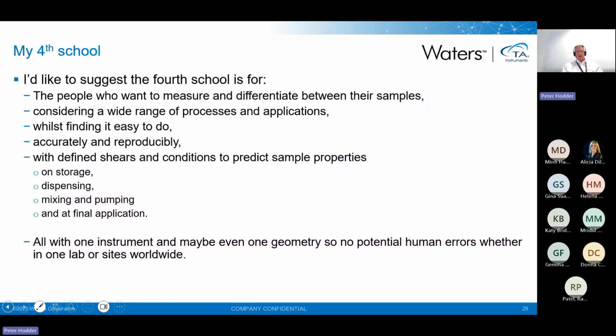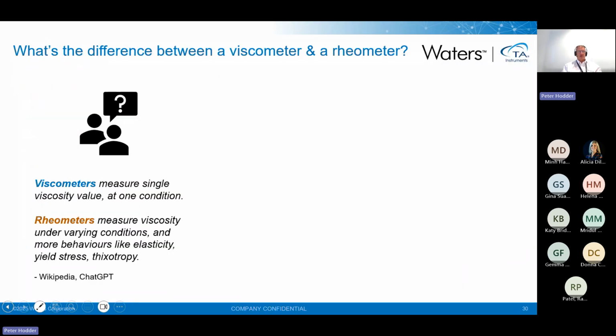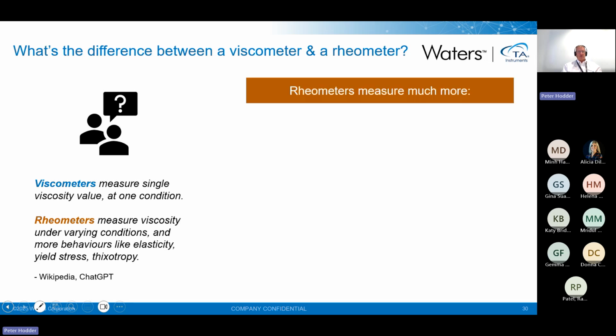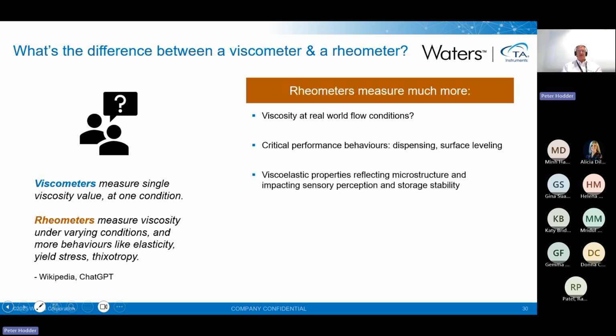So I'm suggesting now that we're really bridging the gap between a viscometer and a rheometer. Now, ChatGPT will describe a viscometer as measuring a single viscosity value at one condition, whereas a rheometer can measure viscosities over varying conditions and more behaviours like elasticity, yield stress, thixotropy, things I've already perhaps mentioned in the past. It can measure more over wider real-life conditions. It can look at critical performance behaviours like dispensing or surface levelling, storage or whatever. It can define viscoelastic properties to actually reflect the microstructure and impact things like sensory perception or storage performance. And it can look at not only liquids but semi-solids and even follow gels.